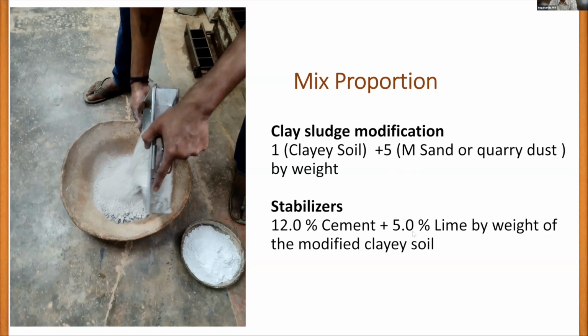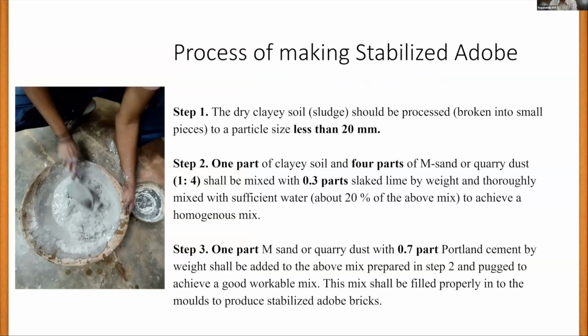To achieve that, we had to do quite a few experiments repeatedly and then come up with this mix proportion wherein we use one part of this clay soil or clay sludge to five parts of manufactured sand or quarry dust or any sand-like material by weight. It's all by weigh batching. Then the stabilizer used here has been 12% cement and 5% lime by weight of the modified soil. That is 1 + 5.